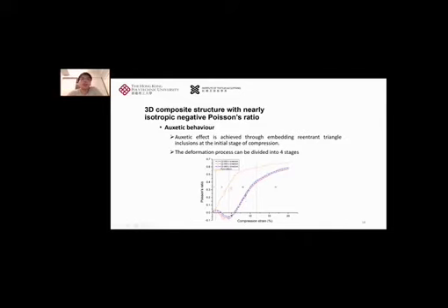The orange line shows the Poisson's ratio variation of the pure silicone. We can see it has 2 stages. Firstly, it increases rapidly with the compression, then it increases gradually after it reaches around 0.5 of the Poisson's ratio, and then it gradually increases with further compression.